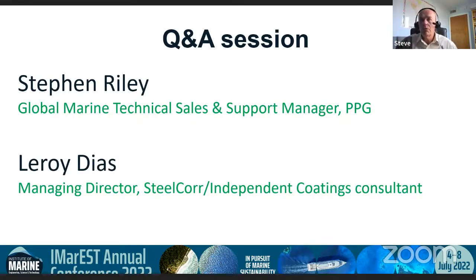So does that mean we should move away from aluminium? Well, aluminium has some benefits and some drawbacks. One of the drawbacks is that the way it comes to us in the industry is as a paste. We don't have aluminium particles, we have aluminium paste, and that has its own solvent content. So whenever we start putting aluminium into a coating, that contributes to the VOC content. To have a solvent-free coating containing aluminium is a complete contradiction, because the way the aluminium is used has solvent. So by definition you've not gone solvent-free.